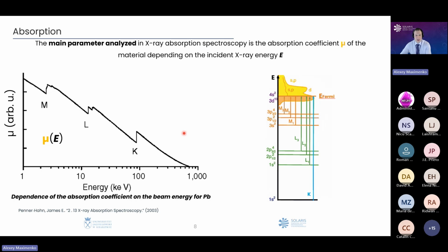And depending on what kind of energies we use and in what kind of range we provide these measurements, we will speak about K absorption edge, L absorption edge, or M absorption edge. And during my presentation, you will hear, okay, this spectrum we measured at the K absorption edge of vanadium, for example, and it means that we actually excite the electron from the K shell of vanadium, and see what is going on with this excited electron.